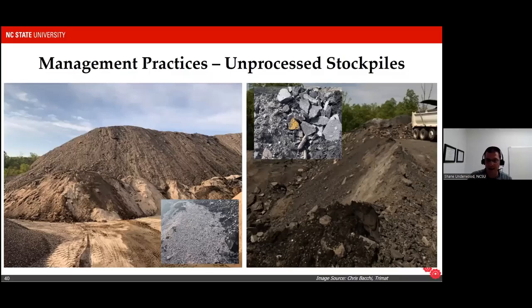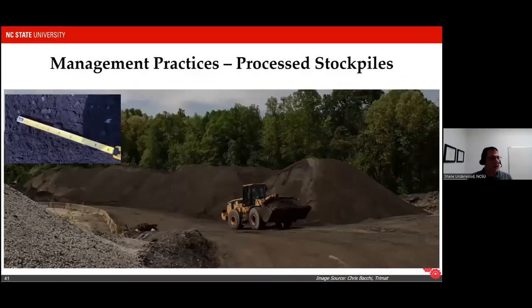Ideal practices. Here we have a contractor that does a very good job, right? The stockpiles aren't too high. They've got an excavator that's turning over the stockpiles pretty regularly. The stockpile is dark black, which means it's got a consistent asphalt binder to it. And in fact, this happens to be a very fine stockpile. And you can see, again, how they're managing this to prevent segregation and follow through on the best practices for the city, for the state.